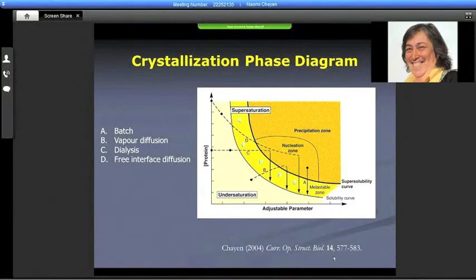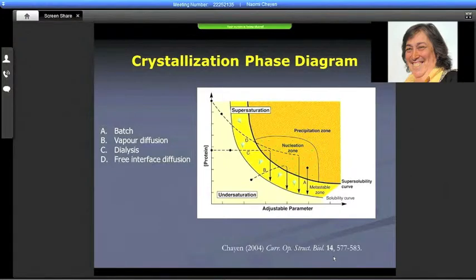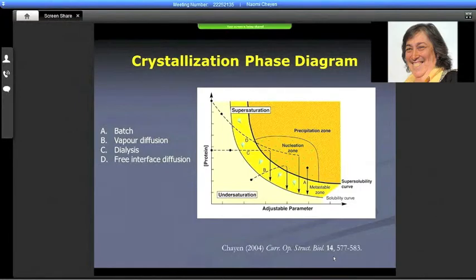The nucleation zone is where nuclei form. To have any crystallization, you first have to have a few nuclei which will grow into crystals. But the ideal conditions for growth is the metastable zone, where crystals will grow but no further nucleation takes place. The problem with crystallization is that if it sits in the nucleation zone and stays there, more and more nuclei form and one just gets showers of tiny crystals. The lines marked A, B, C, and D represent the four major crystallization methods, and all of them have to somehow get to the nucleation zone and make their way to the metastable — they just do it via different kinetics.